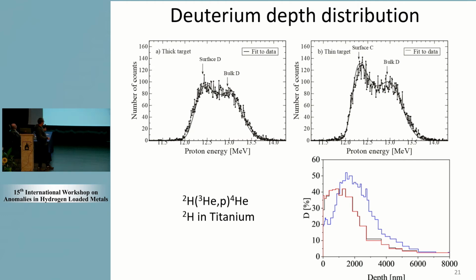Then we clean the surface mechanically so that we get all the deuterium on the surface. That's the red one. And then after the experiment, we have the black curve. So it's important that the distribution doesn't change during the experiment. So using this distribution, we can then determine the electron screening potential.